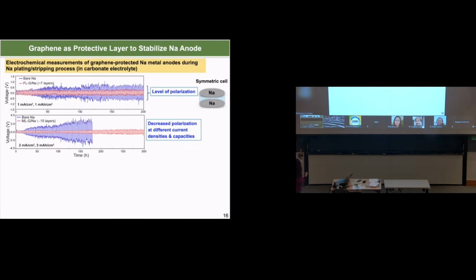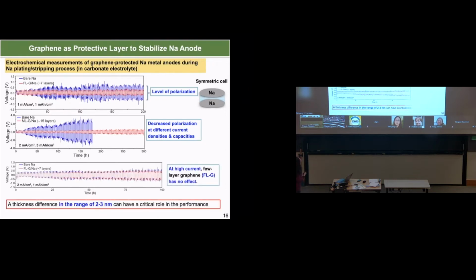Okay. So here I just want to show you a piece of bare sodium, and compare it to this, which is a few layer graphene coated sodium metal. You can see we actually got a much more stable sodium metal cycling performance compared to a bare sodium metal. This is another case, where we cycle the battery at a high current density with a high capacity. So you can see the difference is more dramatic here.